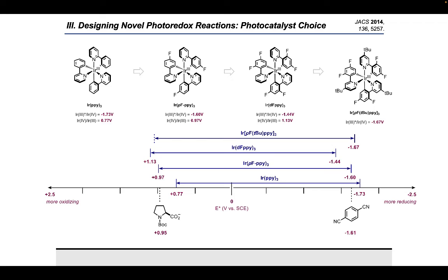Now, with a tert-butyl substituent on the pyridine, we finally arrive at their optimal catalyst, which has a slight overpotential for the reduction. And while the paper did not mention the exact oxidation potential for this catalyst, presumably there is also a slight overpotential as well for oxidation. So these changes allowed them to optimize their yield from 12% using iridium PPY3 to 68% with this final optimized photocatalyst under identical conditions. Then further changes to the base brought the yield up to 83%.